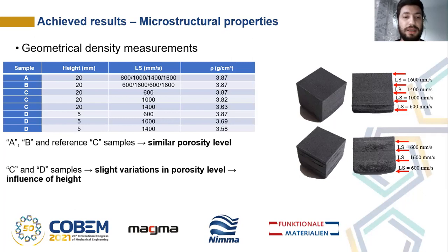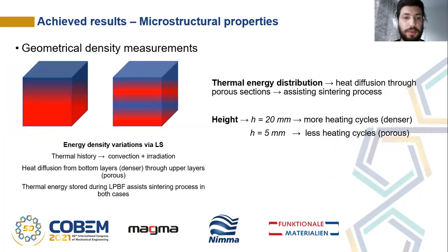Comparing the C and D samples, it can be seen that samples with 5 millimeters height were systematically more porous than those with 20 millimeters for all laser scan speed values explored. The results show that regardless of the strategy adopted, all conditions resulted in similar porosity levels, possibly due to thermal effects of the very nature of the LPBF process.